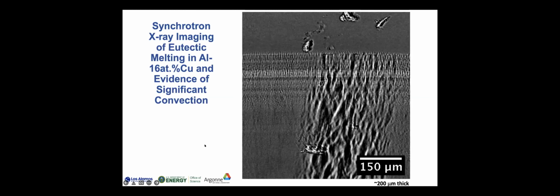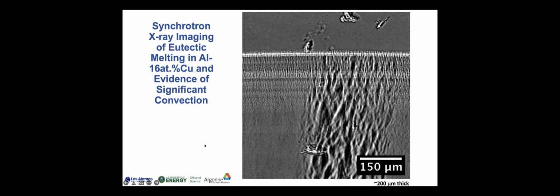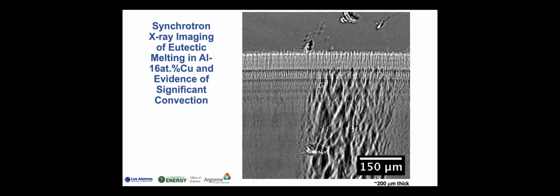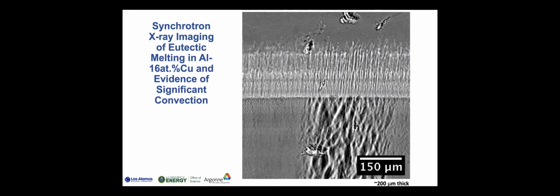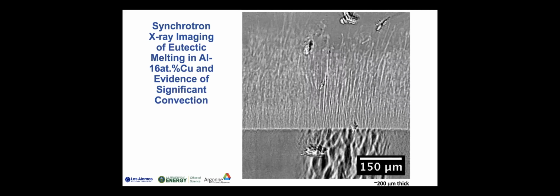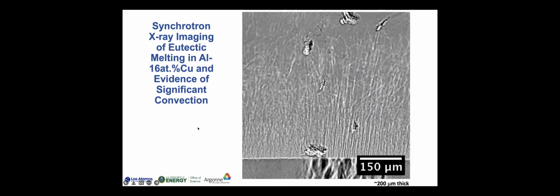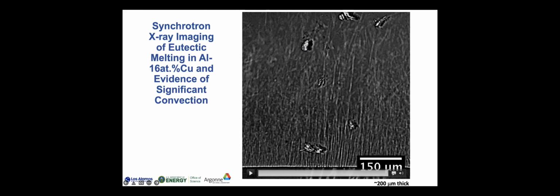You'll see the breakup of this eutectic structure. Here, the bright phase is our aluminum rich phase, and it kind of breaks up in sort of a matchstick kind of morphology. And again, the aluminum rich phase is lower density, it's more buoyant. You see it floating off into the melt, and you see evidence of some convection in the melt as well.